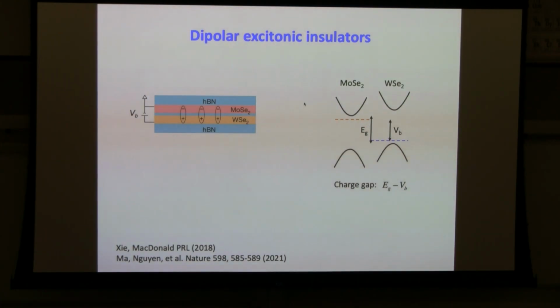These two layers, first of all, have a type 2 band alignment. The meaning of this type 2 band alignment is that there is a conduction band minimum in one of the layers and the valence band maximum in the other layer. The energy separation between this minimum and maximum is Eg, which is the band gap of this double layer structure. Under this bias voltage, it separates the electron and the hole chemical potential, which are represented by these dashed lines here, by an amount equal to VB.